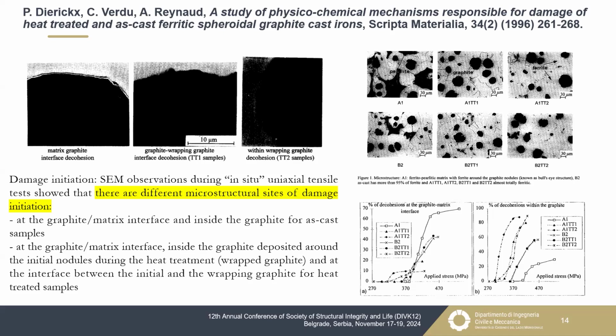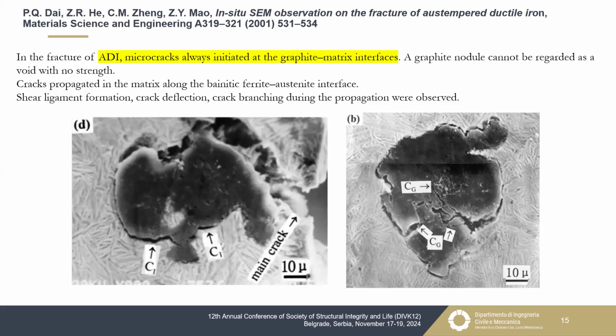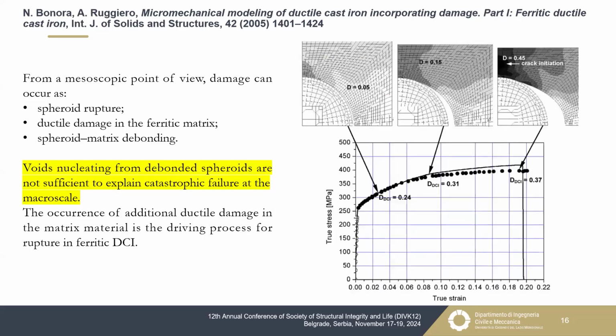And instead, in the case of the presence of this wrapped graphite around the previous nodule, a sort of internal debonding inside the matrix. Considering different matrices, in this case, for example, on a austempered ductile iron, some other damaging mechanisms were found. For example, the shear ligament formation, crack deflection, crack branching during the propagation.